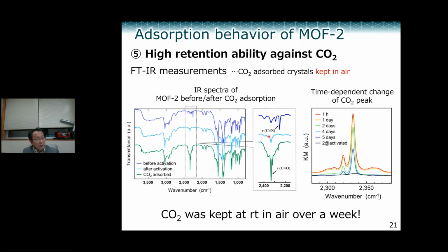Then we monitored the time-dependent change of the CO₂ band at room temperature in air. This is right after 1 hour. Then this is 1 day later, 2 days later, 4 days later, and 5 days later. So you can keep CO₂ at room temperature for almost a week. This material surprisingly retains CO₂ at room temperature for a long time.